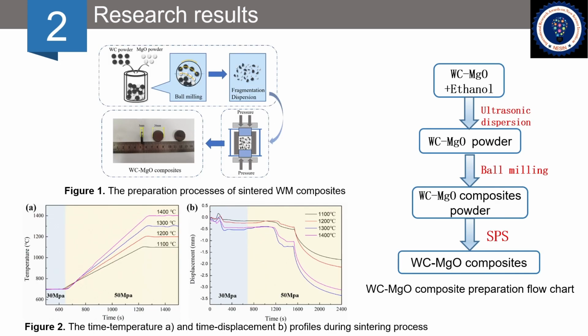Commercial powders of tungsten carbide and magnesium oxide were used as the raw materials. In order to break the agglomerates and refine the size of the composite, the powders of tungsten carbide and magnesium oxide were placed in a ball mill to mix, as shown in Figure 1. Based on our previous work, the mass ratio of tungsten carbide to magnesium oxide of 96 to 4 was adopted. According to the mass ratio of 10 to 1, the powders and cemented carbide milling balls were put into the container and mixed for 50 hours at 350 revolutions per minute in vacuum. Next, tungsten carbide and magnesium oxide composites are called WM composites for short.